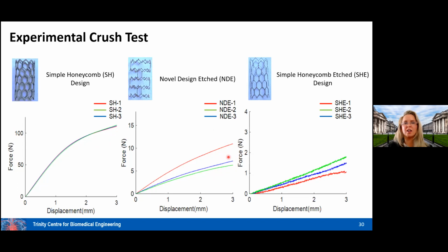There's some variation. Again, this was because there was some variation also in the etching, and you saw that in the strut sizes. And the same with then the simple honeycomb etched, which went to the thinnest struts, needed the lowest force to compress it. So it had the lowest radial stiffness, so the greatest compressibility, this simple honeycomb etched. And again, a little bit of variability, because there was variability following the etching in the strut sizes. And that was again, we need to do more control studies on the etching. As I said, this was more of a feasibility study. Is it possible to do this? And can we use this technique?